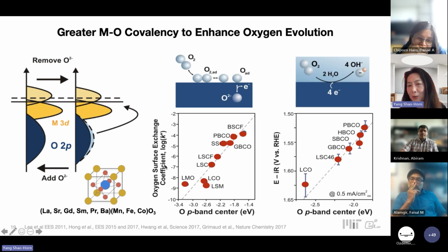for oxygen converting to O2 minus, or O2 minus converting to molecular oxygen, and correlate this rate of the reaction with the computed oxygen P band center relative to the Fermi level. Essentially, you can compute the centroid of the oxygen p band relative to the Fermi level, which is related to the top of the valence band for the transition metal, and is bound by the filling of the d states and the position of the d states. And you can see from the central graph that as we go from lanthanum manganite to, let's say, barium strontium cobalt iron oxide, the rate of the reaction can be increased by 6 orders of magnitude.